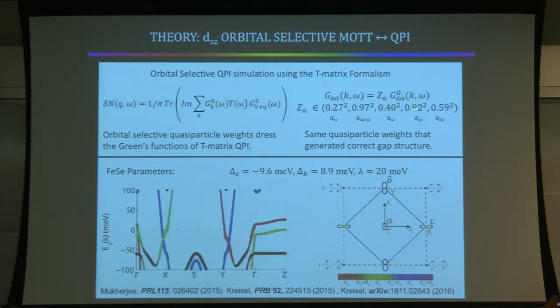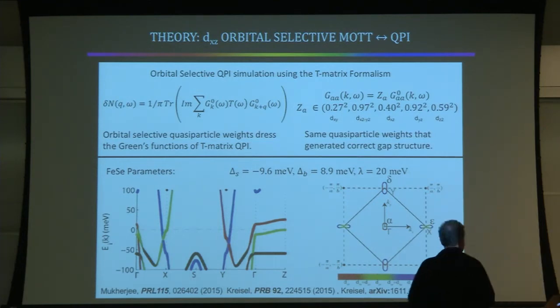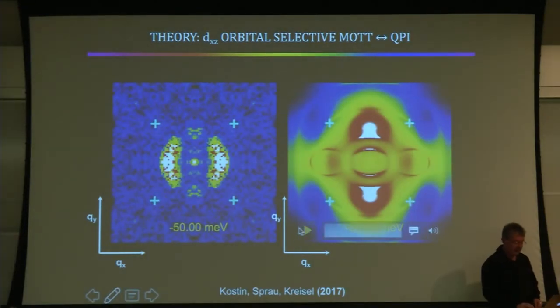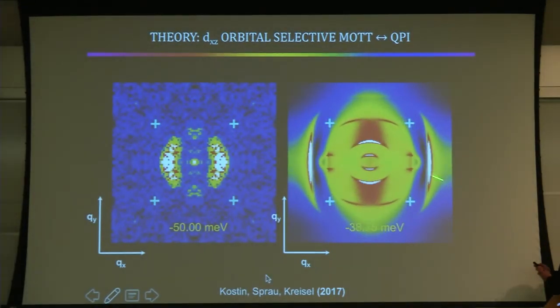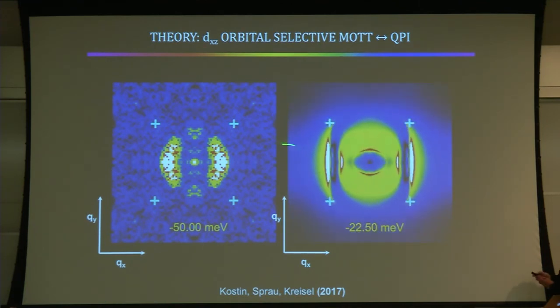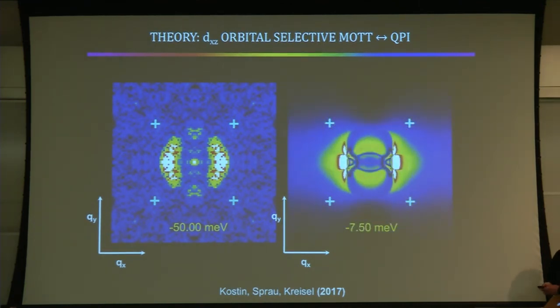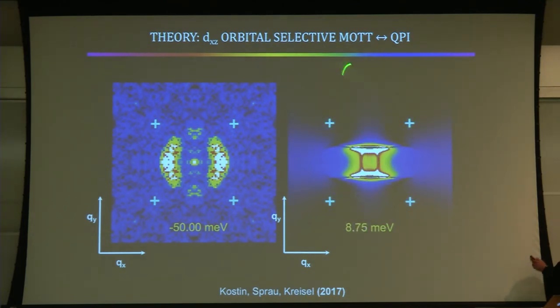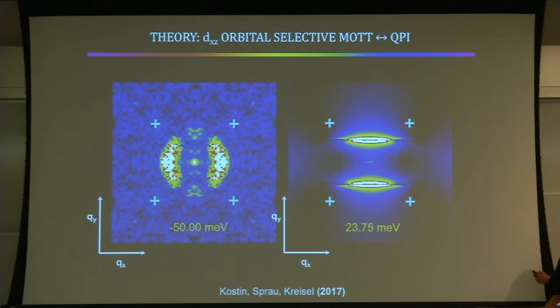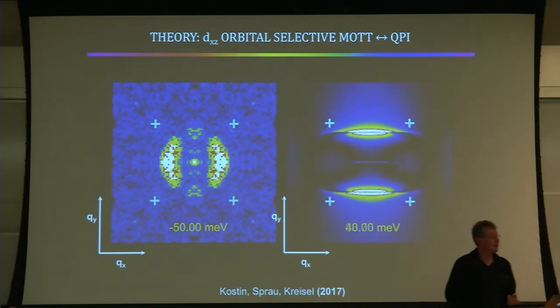Now, we know the values of these numbers. There's actually only one important number. If the Z of the xy is suppressed to a very small value, approaching localization, then it's just the ratio of the Zyz and the Zxz, the ratio of these two numbers, which controls what happens in the quasi-particle interference. So now we do the calculation for this set of quasi-particle weights. It looks like this. It's highly anisotropic along the crystal A axis because we've knocked out the orbitals in the other direction. And then when you come to the chemical potential, it rotates because the dyz band is along the B direction above the chemical potential in this band structure model.